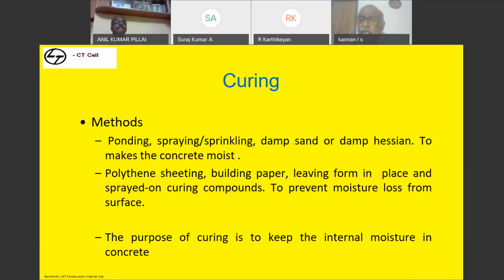People will say the concrete is dry when you are not pouring water on it. Why it matters if it is dry is that the internal water will come to the surface and it will start cracking. So those things can be avoided by providing a curing medium. You don't necessarily have to flood. You have to keep the area moist. If you are able to keep the area moist, then the cracking tendency can be minimized. Normally, after finishing, if possible, cover it totally with a plastic sheet or put a hessian cloth and sprinkle water.